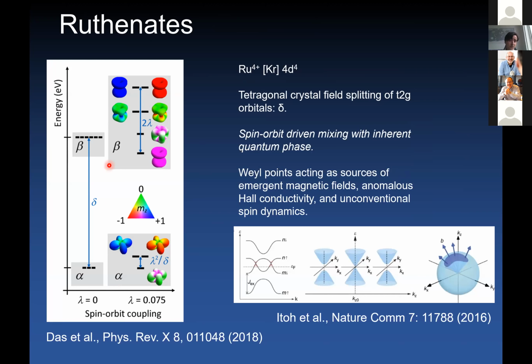So this is characterized by this energy scale delta, and you have this part of your electronic structure that is mainly characterized by, so all the orbitals are mixed, but here you are mainly of the XY character, while in this section of the manifold you are mainly of the YZ and the XZ character. And when you again spin-orbit split this structure, you create an entanglement of orbital and spin degrees of freedom. So it's not as strong as in the iridates to create a J-effective state, but still it is strong enough to create a strong entanglement of spin and orbitals with, again, an inherent quantum phase.